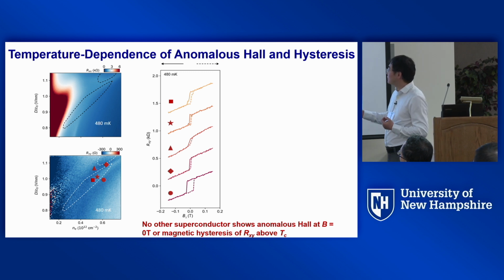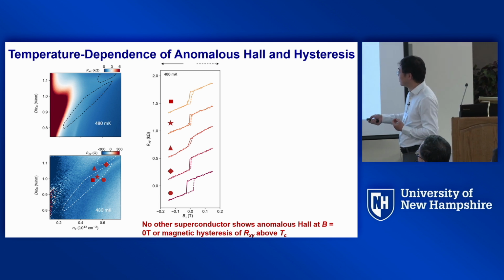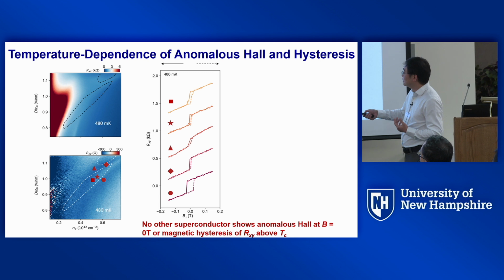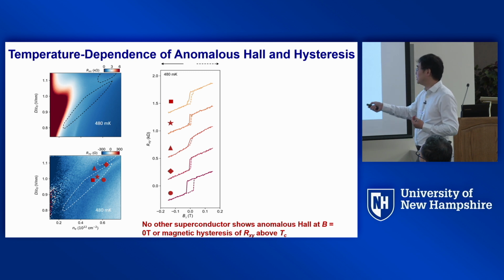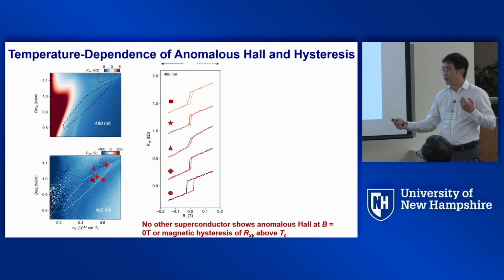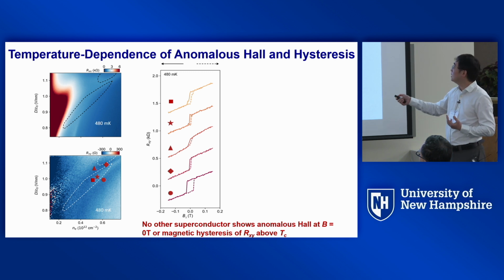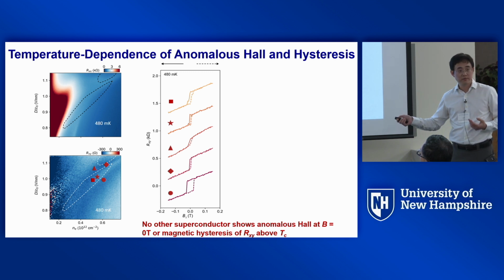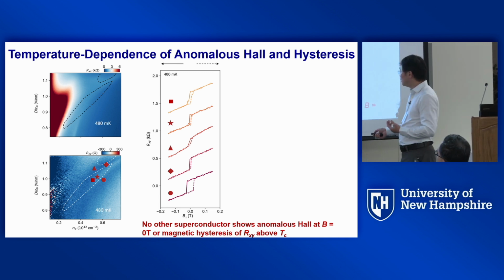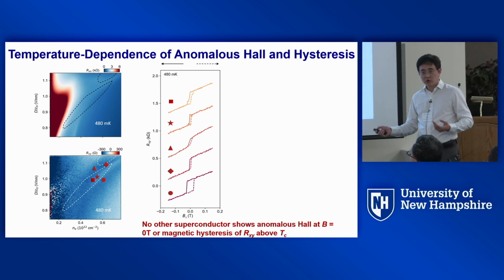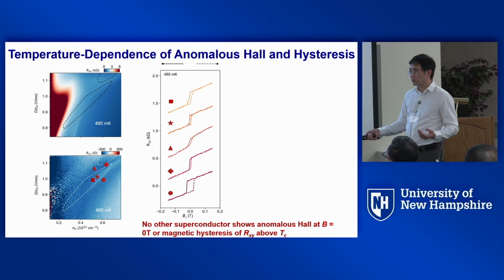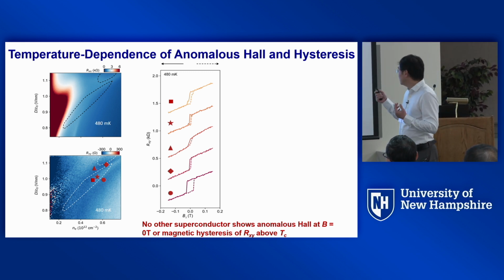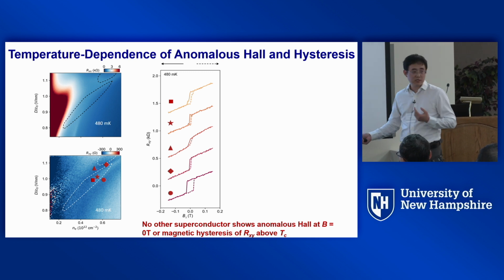And you do have magnetic hysteresis when you sweep the out-of-plane field back and forth. The star and the square are both inside the superconductivity state 1. And there's a clear jump, and there's a hysteresis loop. And if you cut at B equals 0, you get spontaneous time reversal symmetry breaking and a non-zero value of Rxy. As far as we understand, this is the only pure material that shows magnetic hysteresis and anomalous Hall above Tc.